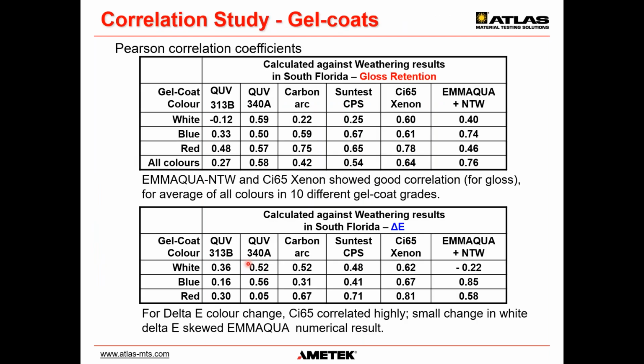And overall, they did an evaluation on the gloss and on the color change of all of the specimens. And the question was, which of those test scenarios gives the best correlation to Florida weathering? And overall, looking at the gloss and the color change, UVB did not show good correlation. UVA a little bit better. Carbon arc also not a very good correlation, especially when it comes to gloss. Maybe a little bit better when it comes to color change.